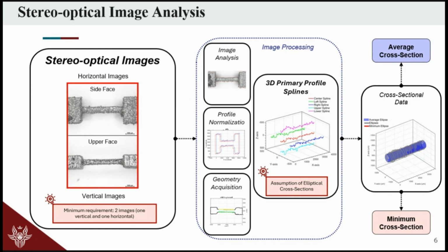collects two images, one horizontal and one vertical image, so basically flipped by 90 degrees with respect to the horizontal image. And through some image processing analysis that has been done in MATLAB, but that can be extended to any other type of solver, we are able, with an assumption of an elliptical cross-section, to build up the cross-sectional data of each specimen over the gauge length, considering thus the average cross-section and the minimum cross-section. We decided to employ the minimum cross-section for the fatigue analysis, as you will see later.